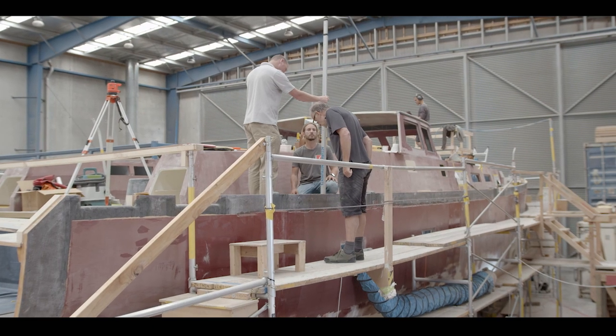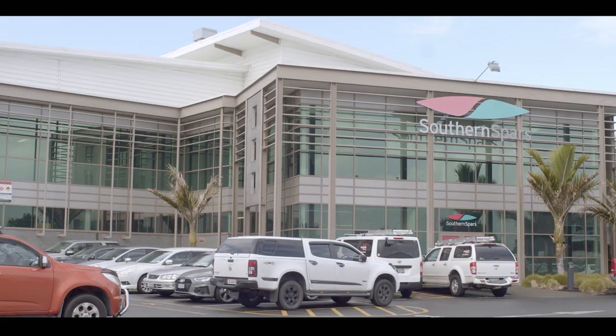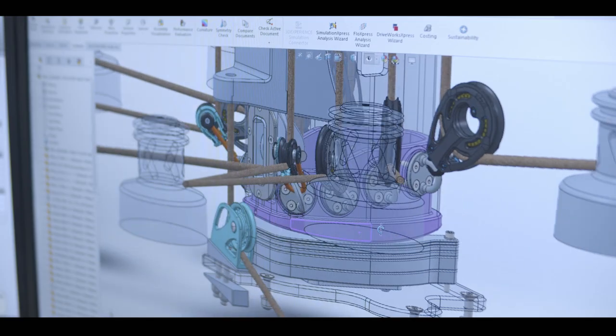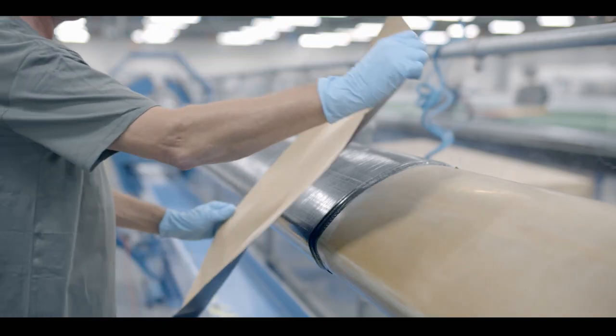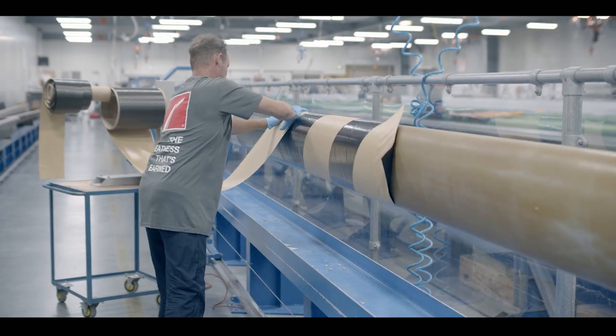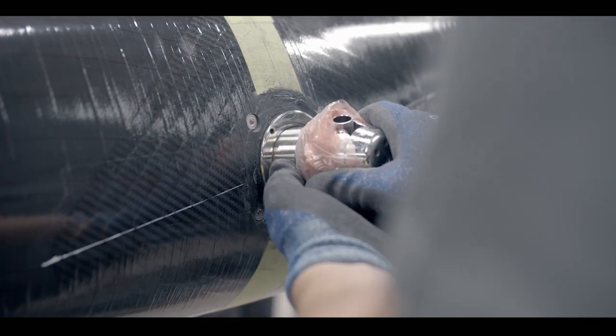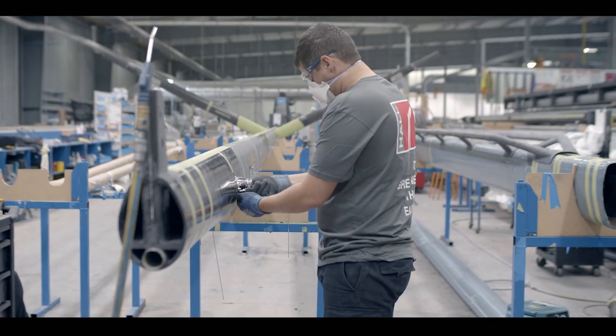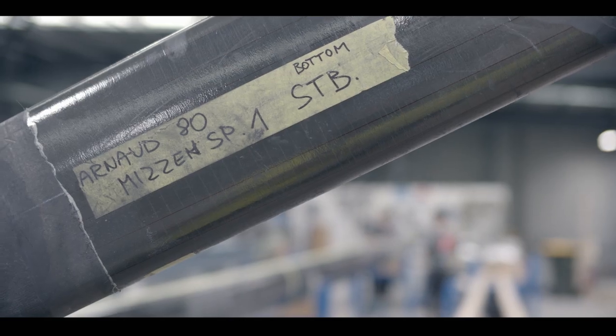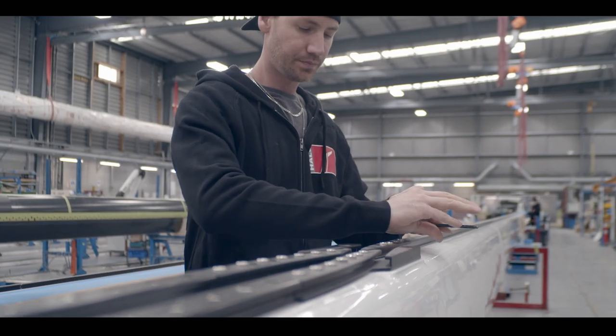In October of 2020, the team from Hall Spars and Rigging came on site to make their final precise measurements for the masts they would be supplying. These carbon fibre masts were made at their factory in West Auckland. Epoxy-coated sheets of carbon filament are wound in a cross-hatch pattern before being covered in a heat shrink tape to compress out the air during the later heating process. Points for mountings and fittings are then created, and all pieces are tested for fit before the mast goes into the autoclave for curing. Once cured and then painted, the accessories are all mounted to produce the final masts.